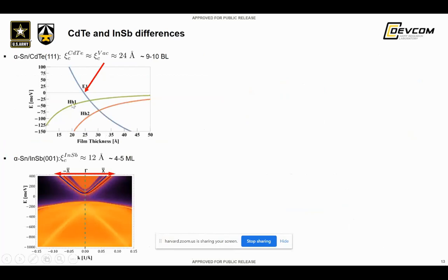The critical thickness typically for CdTe is on the order of say 24 angstroms. That's when you uninvert the bands finally, and you go from a 2D topological insulator to a 2D trivial insulator. And so this critical thickness is on the order of, say, 24 angstroms for CdTe materials, but for InSb, it's on the order of 12 angstroms. That explains why people have seen, in essence, a 3D topological insulator at very thin layers of InSb, on the order of, say, 12 angstroms, which can be attributed to the fact that the band offset is so small and the band gap of InSb is quite small.